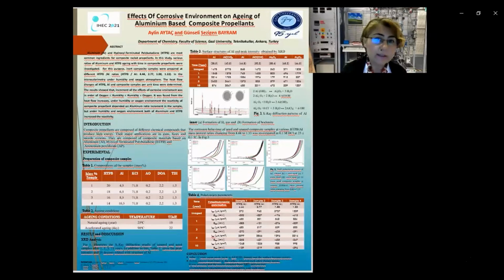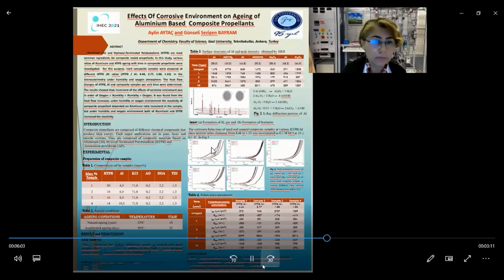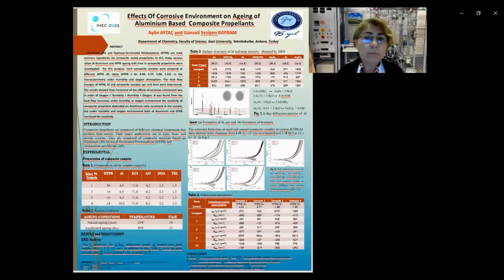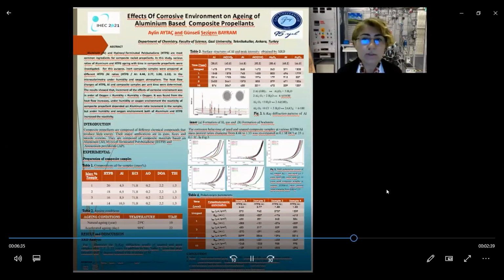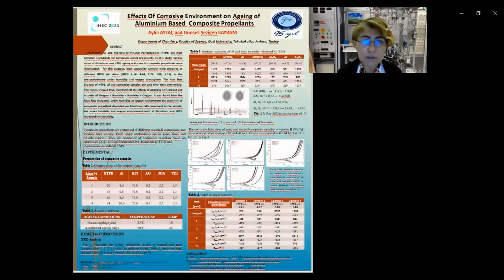If you look at the electrochemical measurement, here we have 1, 2, 3, 4, 5 Tafel plots. The electrochemical parameters such as corrosion potential and corrosion current density obtained from the Tafel polarization curves and the corresponding aging time are given in table 4. From the data, there is an increase of the corrosion current density with aluminum ratio in the sample for the unaged samples, except for sample 3. Corrosion current density decreases after the first year for all the samples.